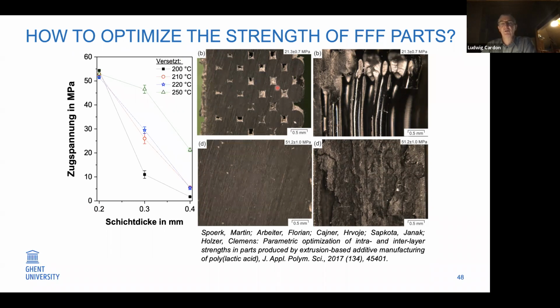That's in the scope of very low temperatures and high layer thickness. Then it looks like this. But when we go to small layer thickness and high temperature, we have almost no voids and we have a better morphology structure of the material. It's the journal I mentioned here, Applied Polymer Science.